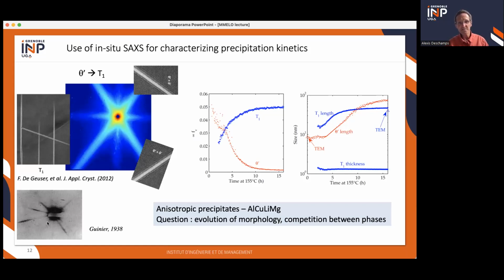So he guessed, looking at these kinds of diagrams, the presence of GP zones and was able to determine the size, the diameter, and the thickness of these GP zones. So if you do that in situ, you can see in some conditions here during aging, you have a replacement of theta prime by T1. You still have a few theta prime remaining. The reason you can discriminate between the two is that they don't sit on the same habit planes. Theta prime are on 100 and T1s are on 111.